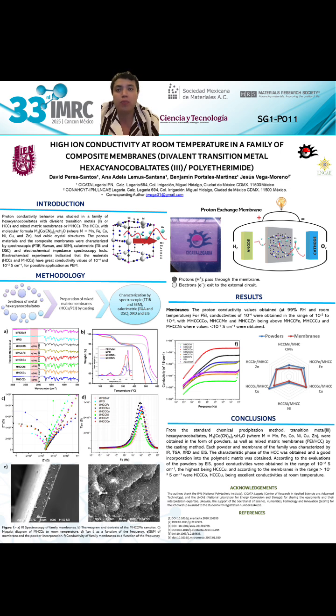As an introduction, proton conductivity behavior was studied in a family of hexacyanocobaltates with divalent transition metals and mixed matrix membranes. The hexacyanocobaltates had a cubic crystal structure. The porous materials and the composite membranes were characterized by electrochemical impedance spectroscopy tests. Electrochemical experiments indicated that the materials have great conductivity, with values between 10^-4 and 10^-2 Siemens per centimeter, for possible application as a proton exchange membrane.